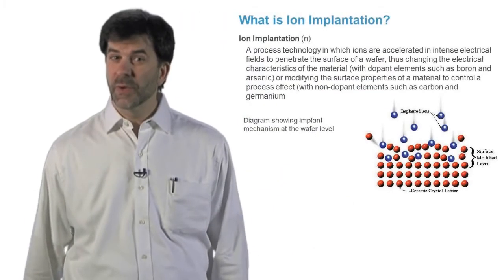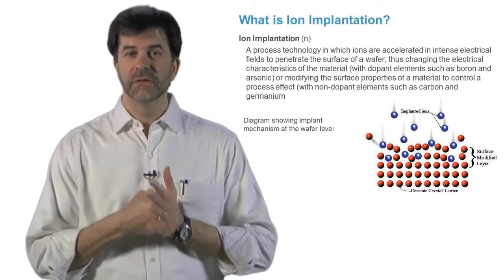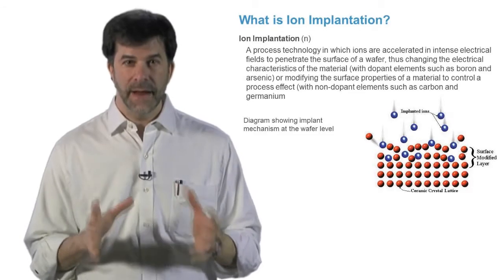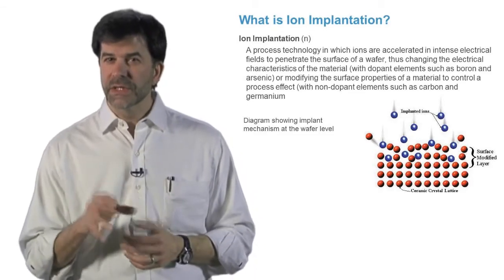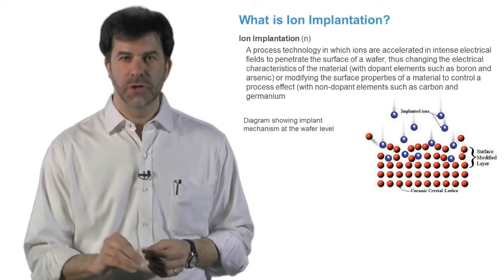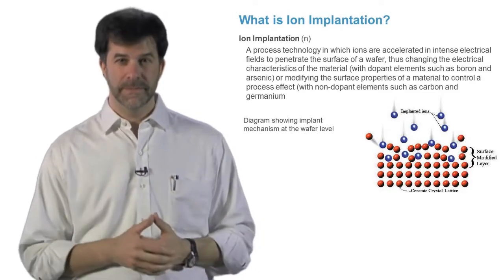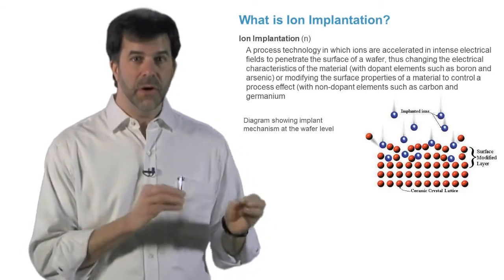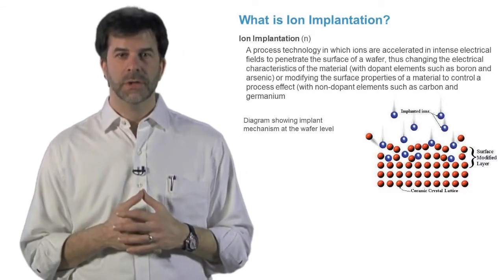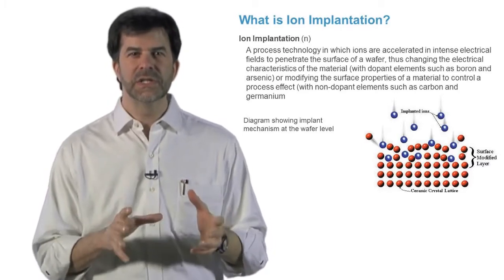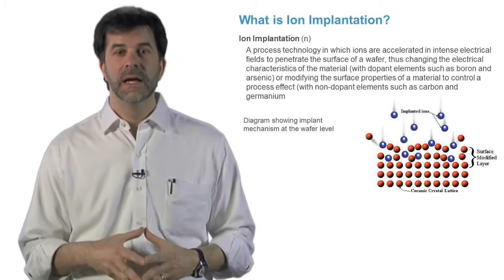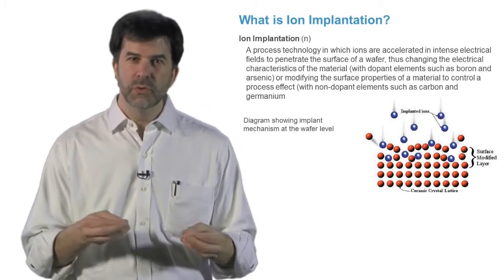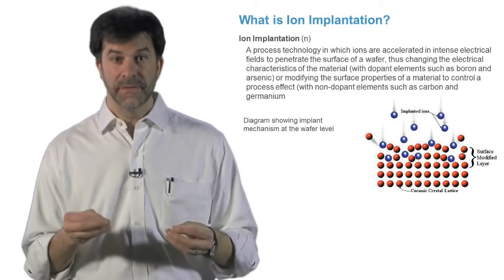Okay, so what happens when an ion crashes into the silicon crystal? Well, there are a whole host of variables that affect what happens to that ion and the crystal after implant. For all implants, the ions disrupt the crystal structure, creating an amorphous layer. The ions are now in an interstitial state, not being part of the crystal structure. By annealing the wafer in a rapid thermal annealing system after the implant, the energy added thermally causes the atoms in the amorphous layer to move to a more stable state, that of a perfect crystal.